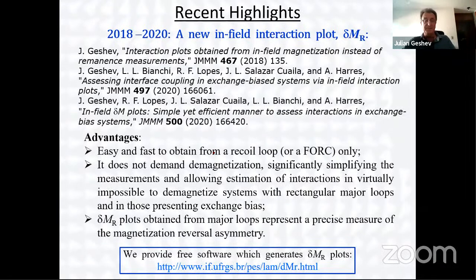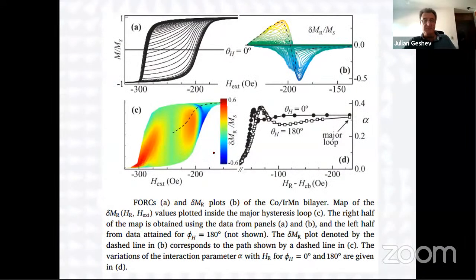If you apply it to a major loop which is asymmetric, for example, in an exchange bias system, you can build this plot for any field, actually, and you have a spectrum of delta MR. You can make a color map of these curves and so on. I'm not getting into details.